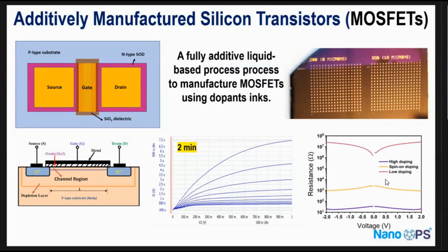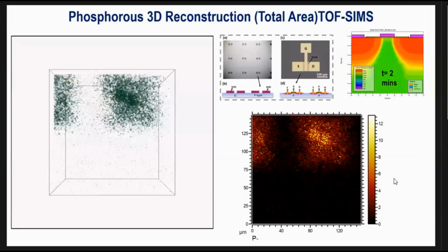In this case, the substrate was silicon, and we printed the electrodes, the metal, but that's not enough. You need to dope, and doping was actually more challenging than printing, because with doping, you use a liquid dopant, and so you have to tune the depth of the dopant penetration into the substrate, and you have to control the concentration profile of the dopant. So this was done actually here.